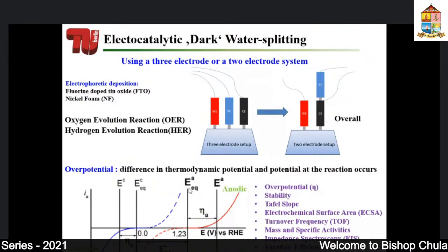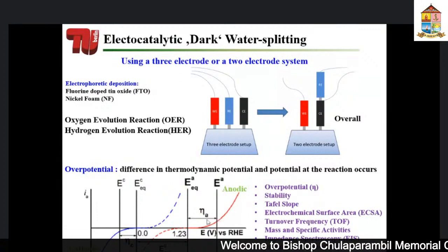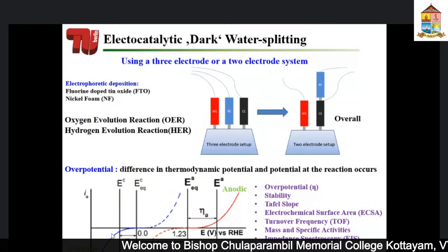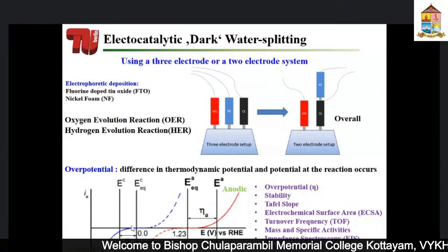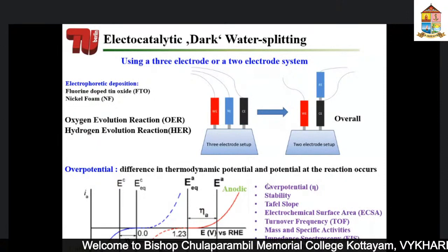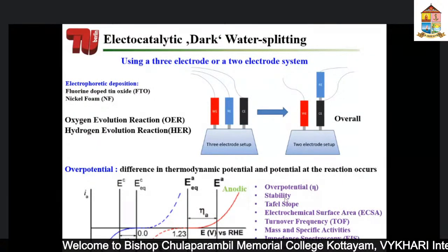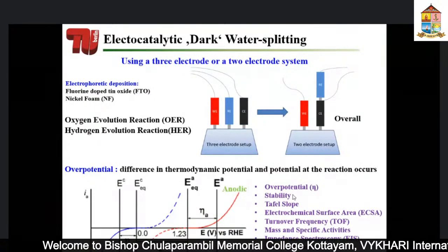So the thermodynamic potential to form oxygen evolution is about 1.23 volts. Whatever potential you apply larger than this is called over-potential. Similarly, the thermodynamic potential for hydrogen evolution is almost zero. Whatever potential you apply here in this cathodic direction is also called an over-potential for hydrogen evolution reaction. So this is a very important factor, and also the stability is a very important factor for this kind